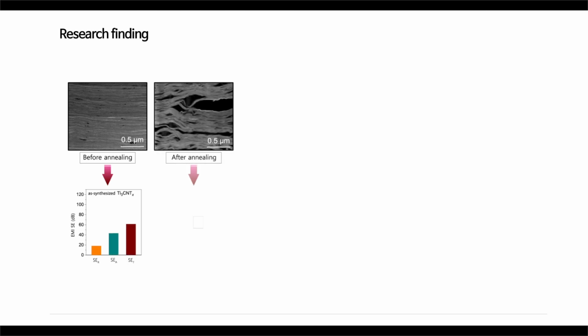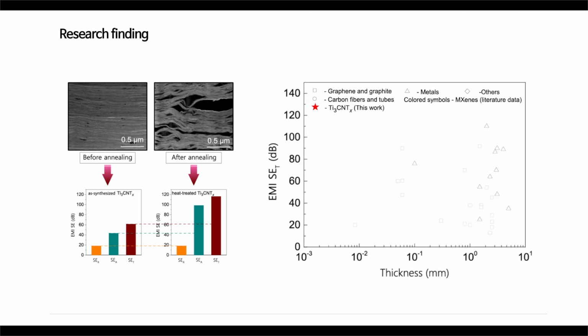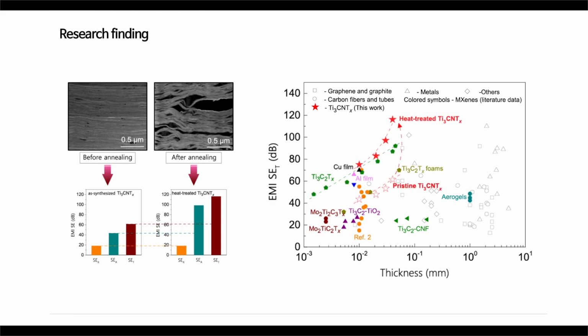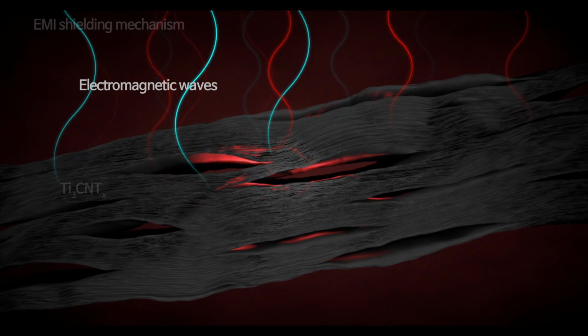A 40 micrometer thick Ti3CNTx film showed an extraordinary EMI shielding performance of 116 decibels due to anomalously high absorption of electromagnetic waves in the layered structure, which is much larger than the 93 decibels measured for annealed Ti3C2 film of comparable thickness. Surprisingly, Ti3CNTx outperforms all other shielding materials with similar thickness studied to date, including copper metal film, which has several orders of magnitude higher conductivity.